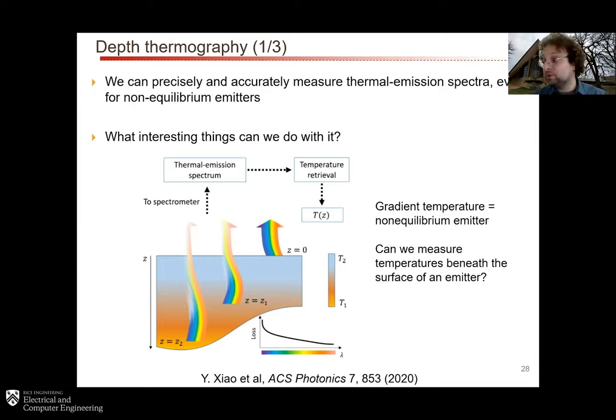So we've had a number of situations where we have a sample that's thick and has a thermal conductivity that's not as high as one might want, either in our reference or in something that we're measuring, and then you have a temperature drop. So this can be quite challenging. So I guess the main caution advice I can provide is to always keep in mind that this is something that you have to calibrate for, and so use some sort of known references in a setup that's as close as possible to what you're actually measuring, so that you can calibrate your measurements. The other thing is, if you have access to infrared spectrometers, I would recommend occasionally sticking your sample in an infrared spectrometer to try to understand what the emissivity is.